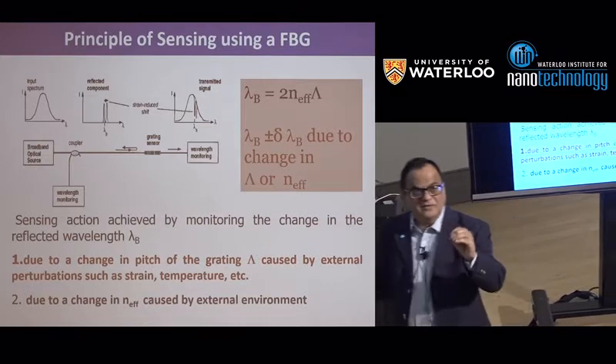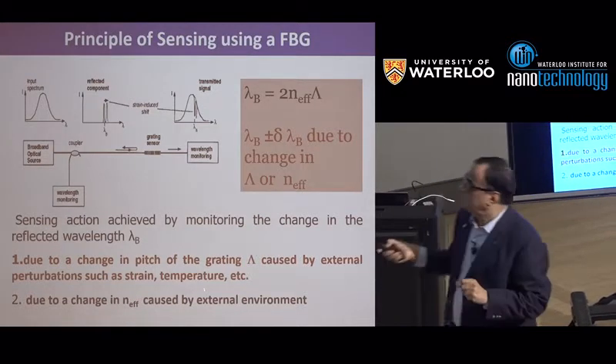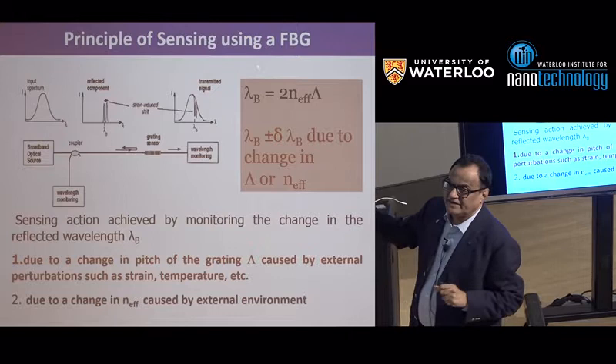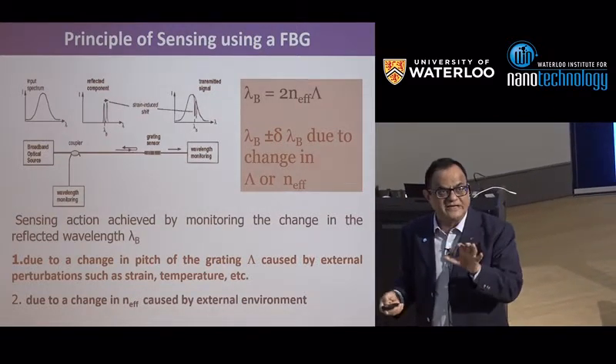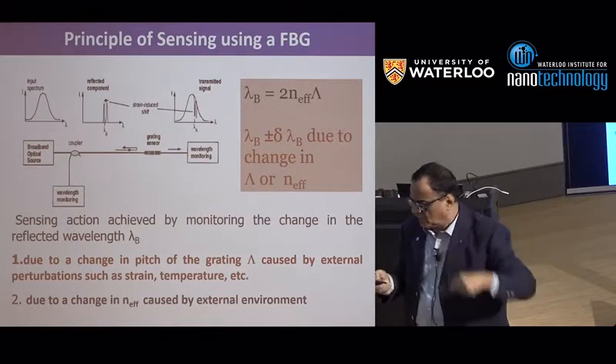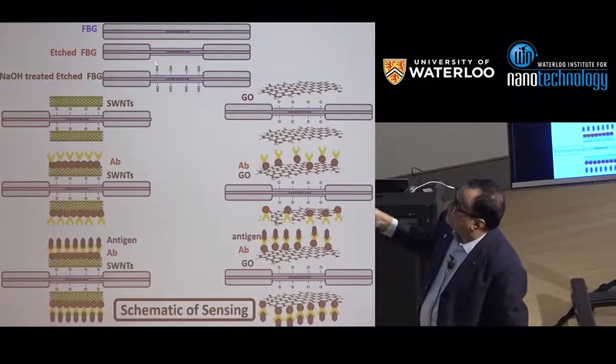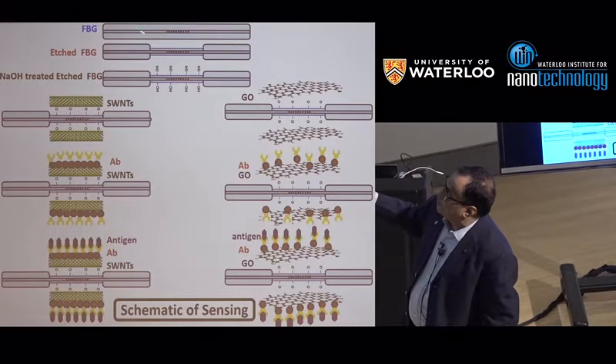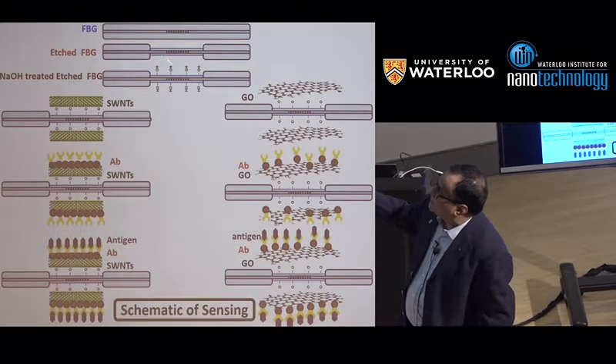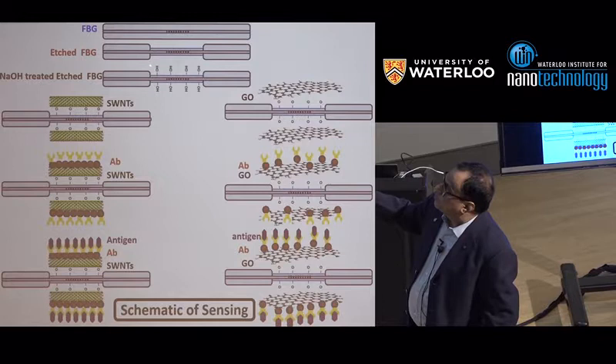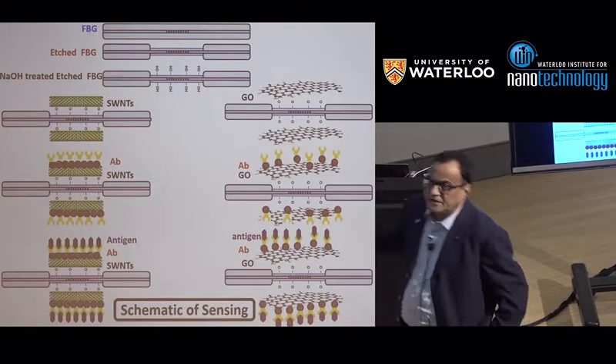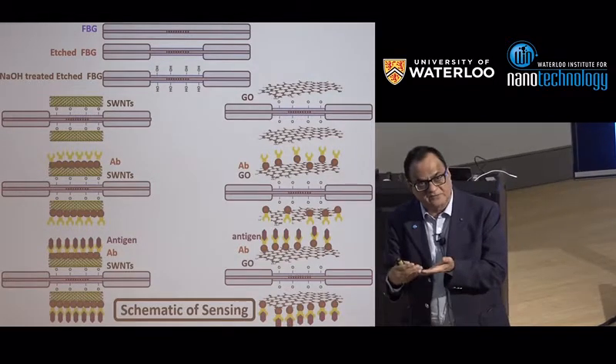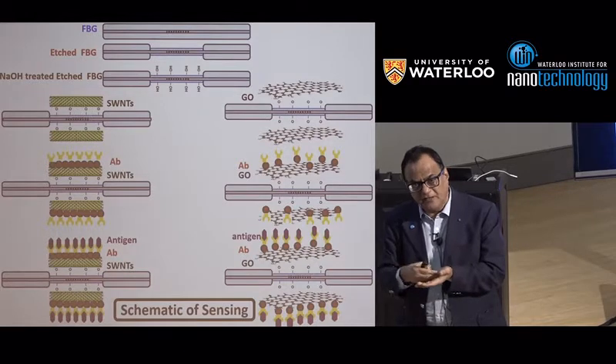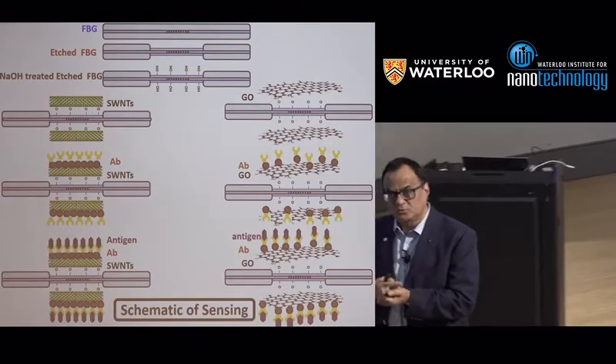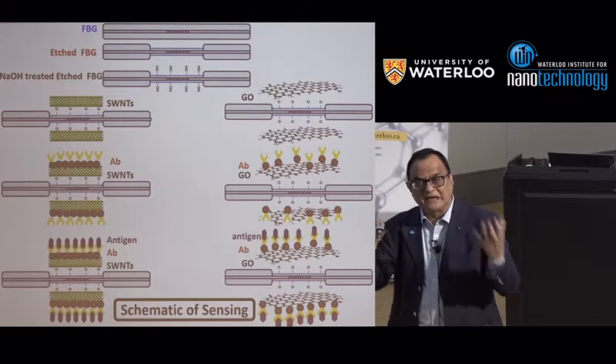So what we are doing now, instead of that, we said let us change n effective, the refractive index of the fiber. Now this is not very easy if you have a clad. So what we did is a simple innovation. We removed the clad in a controlled manner and put the right chemistry to deposit different types of nanomaterials. We tried nanotubes, we tried graphene, now MoS2, you can even use quantum dots. You have to find the right chemistry.